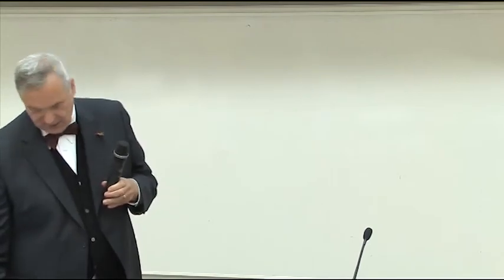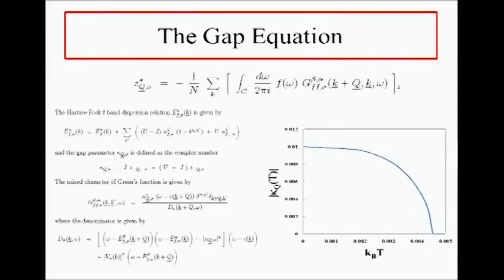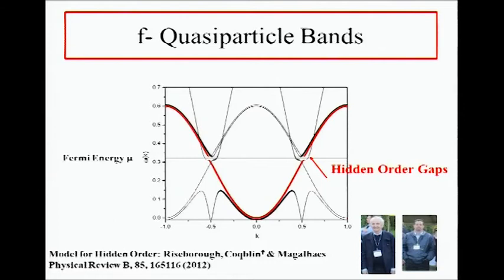If you then do the mathematics and the mean field approximation, you get nice mean field band pictures. This is the so-called hidden order gap as a function of temperature, and it matches quite well with experiments. As you can see from the calculations, it does produce a pseudo gap in the density of states, with states that run through the Fermi level.